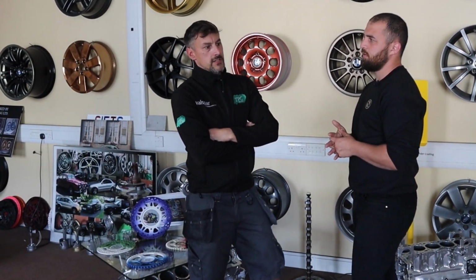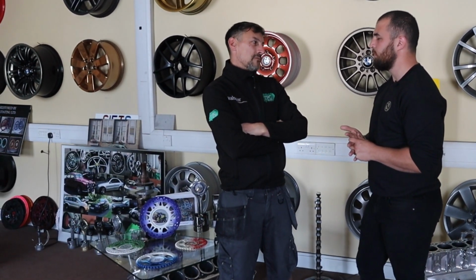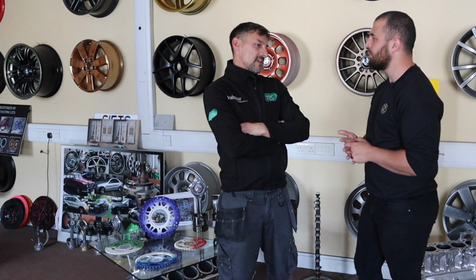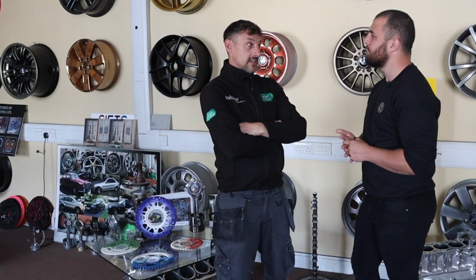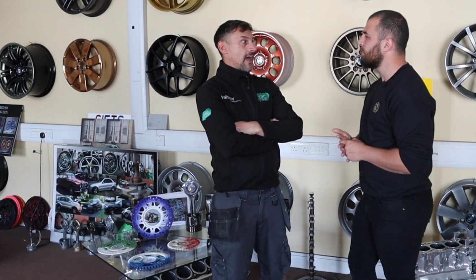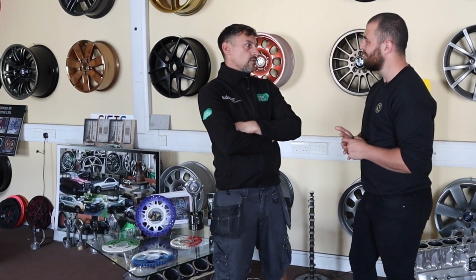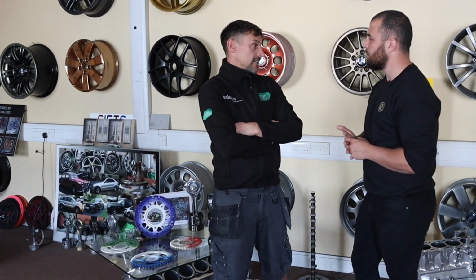I think there's a couple of factors. Firstly and foremostly, experience. 30 years. We were back there years ago when you make the mistakes, whether they were through your own doing. You get caught out on things. I can remember years ago in the early days doing a set of Mercedes wheels. The same set 4 or 5 times, never a problem. And then on the 5th or 6th time, the same set that I thought I'd do with my eyes closed, came out of the oven with holes all over them. That was the degassing that I was talking to you about. Just not knowing that's what you need to do.